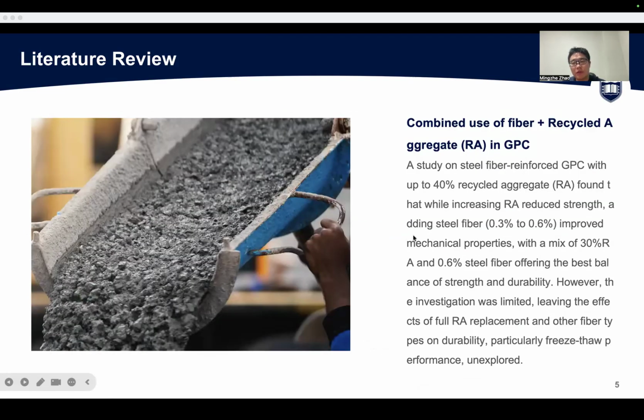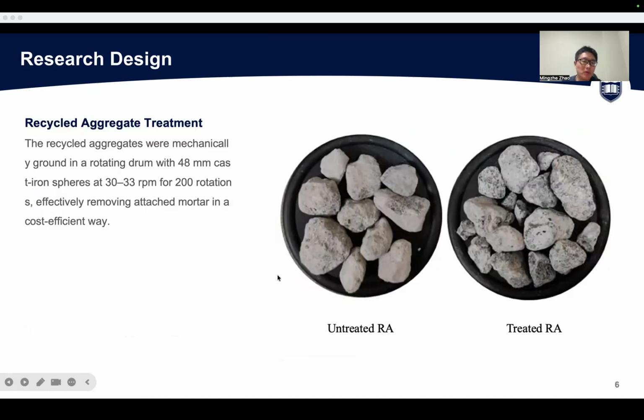And the combined use of fiber with recycled aggregate in GPC. A study also investigated steel fiber reinforced GPC with up to 40% recycled aggregate, and found that the RA will reduce the strength and the steel fiber will improve the mechanical properties. The optimum content is 30% RA and 0.6% steel fiber. However, this study also has limitations. The RA replacement is not 100%, and it only investigated steel fiber. So, coming to my research design.